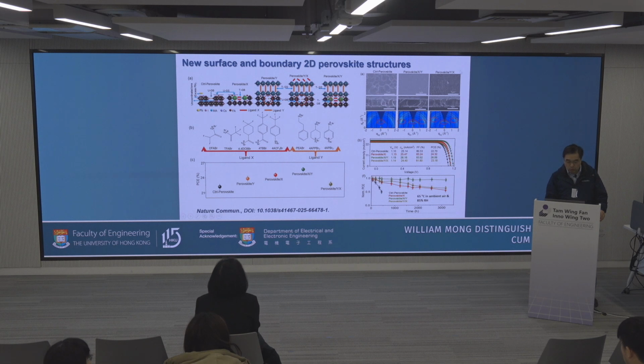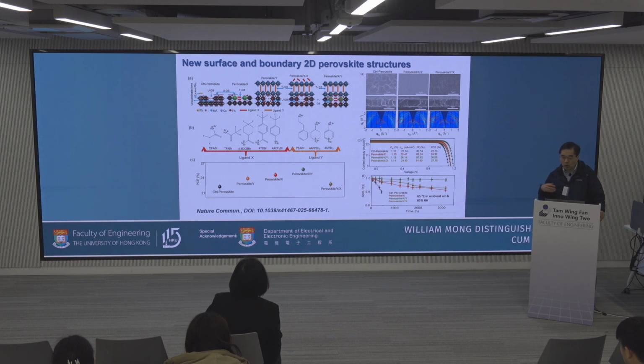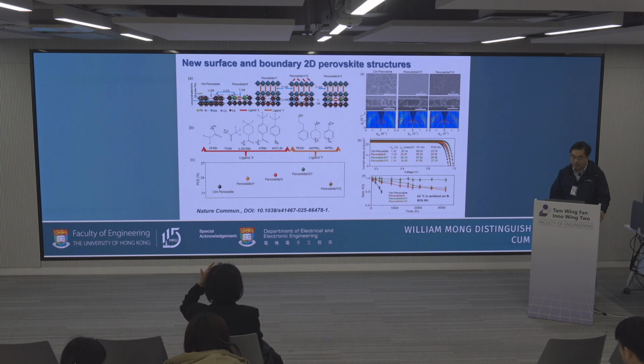So we introduce two groups of ligands, X and Y. X is targeted for the boundary, Y is targeted for the surface defects. What we see is that most of these small molecules eventually help us to form the 2D material. So we are not coating an organic material just on top at the boundary. We are forming 2D material at the boundary as well as the surface. This is evidence that when we introduce X, introduce Y, we can form the 2D materials.